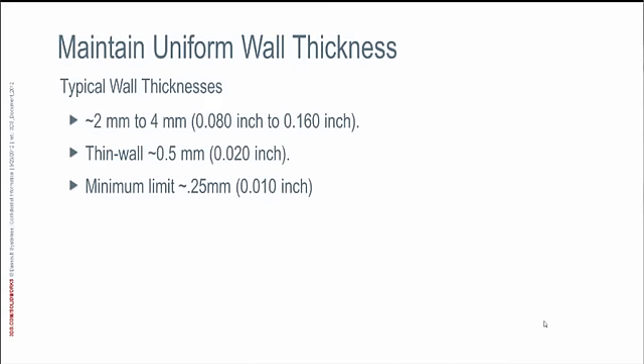When we talk about injection molded plastic parts and maintaining uniform wall thickness, what thicknesses are we talking about? Typically, injection molded parts will have thicknesses ranging from about 2 millimeters to 4 millimeters, or 80 thousandths to 160 thousandths of an inch. I would argue that up around 4 millimeters these parts are getting pretty thick — most parts are going to be 2 to 2.5, maybe 3 millimeters thick.